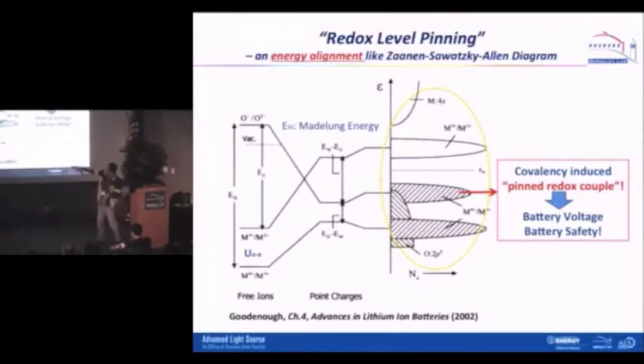After you alter all those original energy levels by this Madelung energy, you will form different kinds of bands. In these bands, typically you have the anion, in this case oxygen 2p if it's an oxide, the oxygen p band, and the transition metal 3d bands. Those bands really determine the property of your material because they are the closest levels to the Fermi level, and the Fermi level is the most important physical energy level to determine the property of the material. So the relative energy position of this 3d state to this anion oxygen 2p state is what Goodenough was talking about with the redox level.